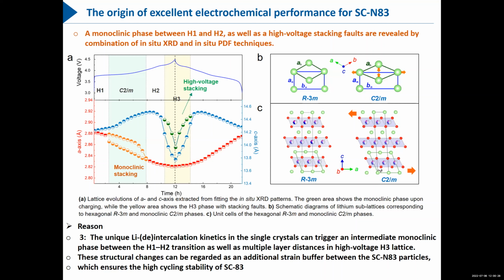So the monoclinic phase transition is very common in lithium cobalt oxide. But when nickel and manganese are doped or mixed with cobalt, we know that the monoclinic phase can be eliminated. Nickel and manganese can help the cobalt to eliminate the order-disorder transition, that means the monoclinic transition. So it's very strange for me to find this kind of phase transition in the single crystal materials. That's why normally it cannot be found in the polycrystalline materials.